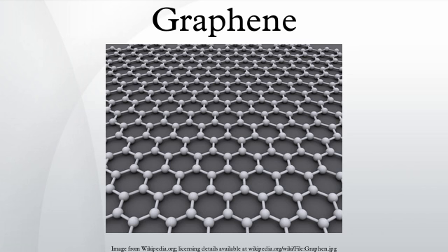Graphene is normally hydrophobic and impermeable to all gases and liquids. However, when formed into a graphene oxide-based capillary membrane, both liquid water and water vapor flow through as quickly as if the membrane was not present. Chemical modification. Soluble fragments of graphene can be prepared in the laboratory through chemical modification of graphite.